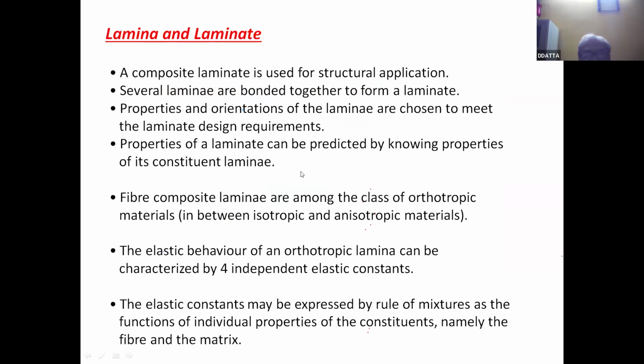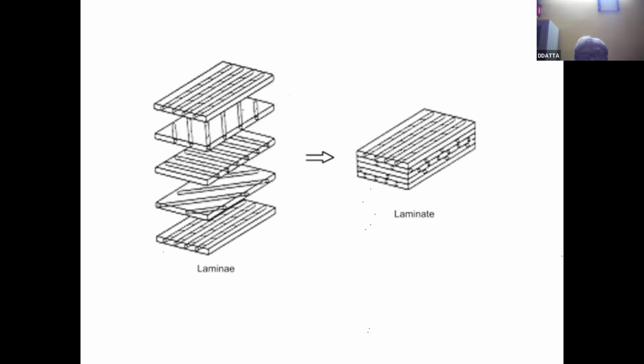Now I have mentioned that fiber composite laminae are among the class of orthotropic materials. They are in between isotropic and anisotropic. Somewhat you can say that an orthotropic material is a material with limited anisotropy. The elastic behavior of an orthotropic lamina, as I said in the previous slide, is characterized by 4 independent elastic constants. We will see what they are. The elastic constants may be expressed by the rule of mixtures, so the rule of mixtures can be applied to find some of the properties of a lamina.